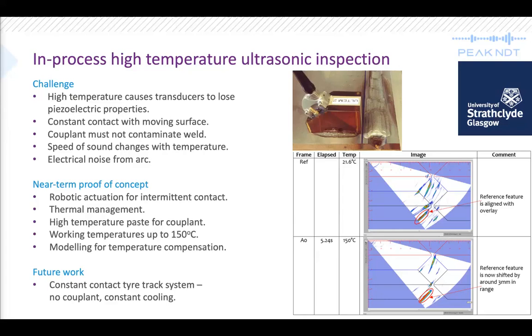And by the end of the program, we were able to demonstrate data collection at 150 degrees C, modeling techniques to compensate for the temperature profile, automated collection of the data from the probes subsequently after welding, and integration of the entire system within a robotic welding cell. So this was performed by our partners at the University of Strathclyde in their welding centre. So a significant stream of the future work of this program is working with them continuingly to develop this technology. Next slide.